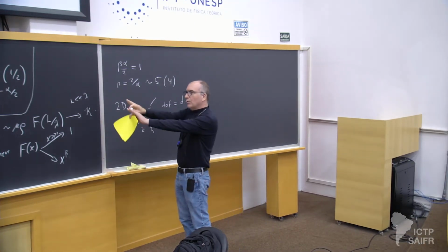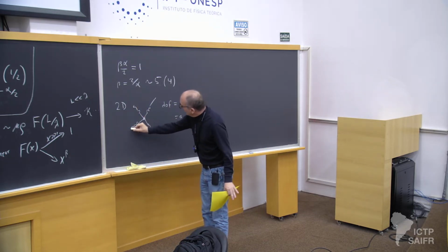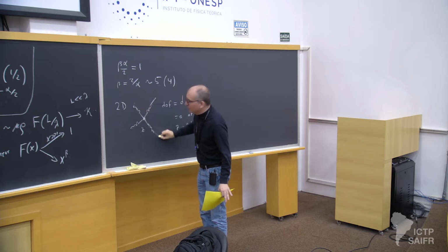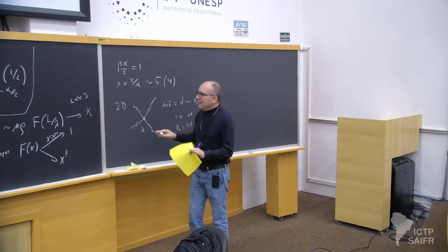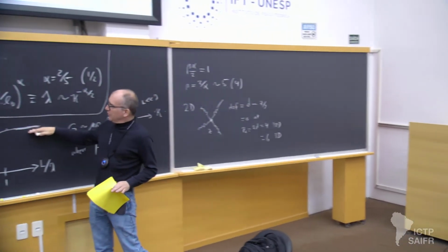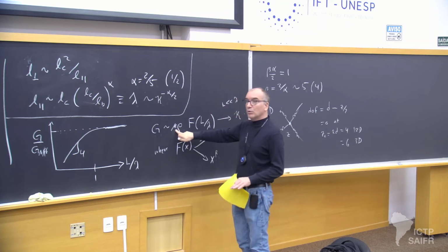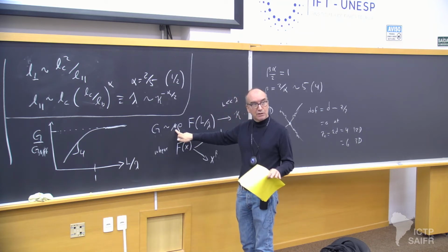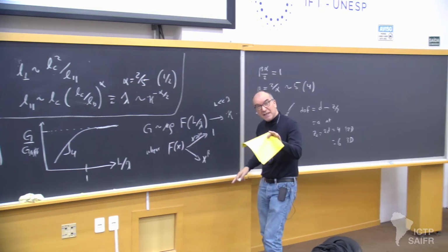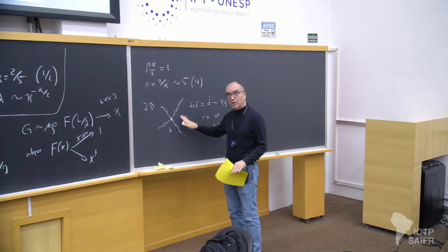Now, one way to look at this is the following. I can replace these by fibers that resist bending as well, but they're going to resist it weakly. If I tell you that the modulus has gone to an entirely affine modulus, which, by the way, is proportional to mu, that means fundamentally the elastic energy in the system is stretch. That suggests that I should be able to account for that mechanics with central forces, right?